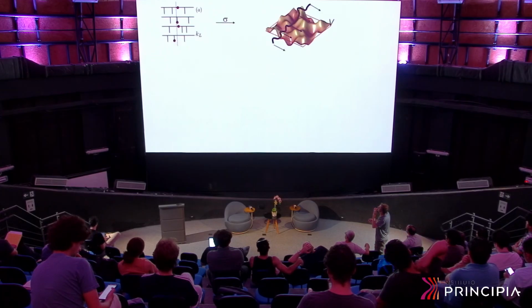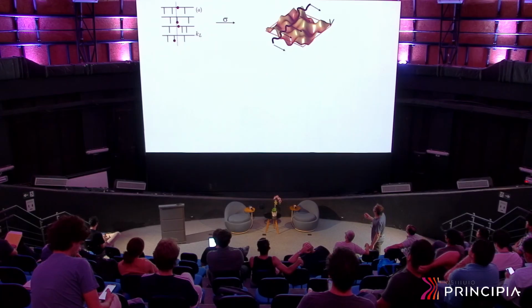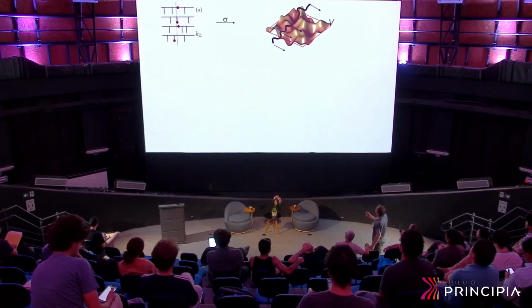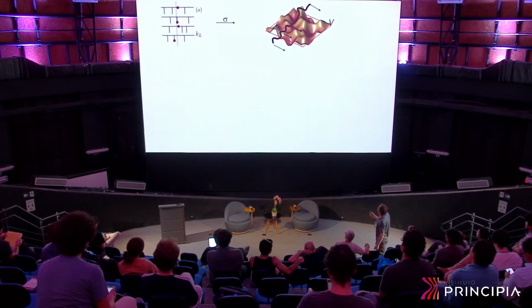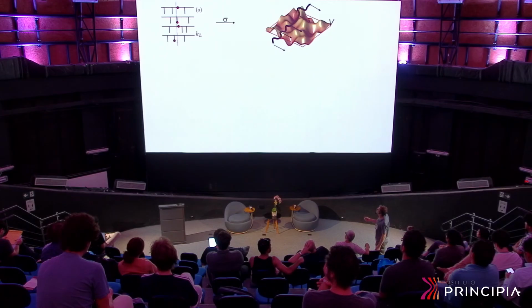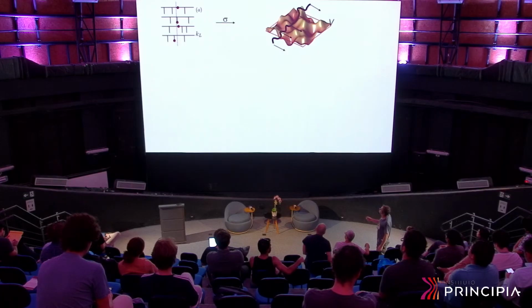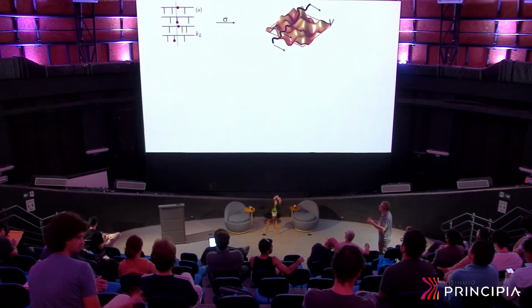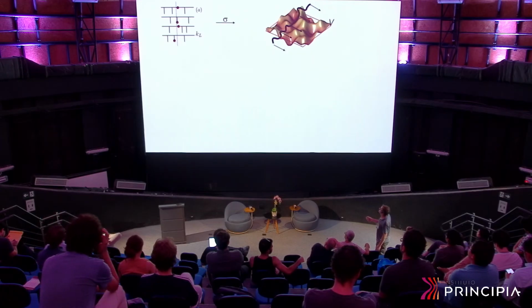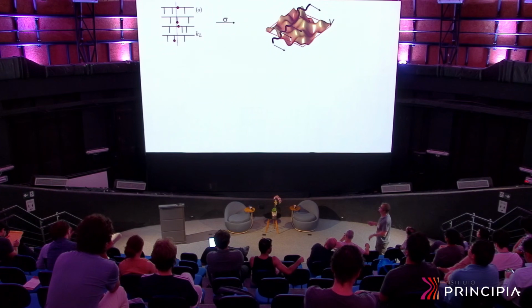Let me give a very naive explanation of the phenomenon for the case of pinning, where we have an elastic string on top of a potential, and what happens when we change the elasticity of this spring. Consider that this string is formed by the points that are indicated here. They should be thought of as joined by springs. And the random potential here is implemented as very well-localized potential wells and some regions that do not have any potential. So in a given configuration for a given value of the spring constant, probably this is a configuration of the system, and this line indicates the mean position of the string.